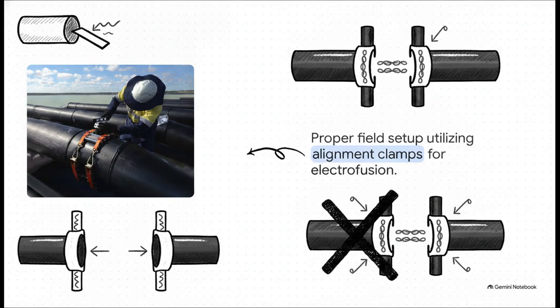But there's a catch. Relying on that internal expansion means your field setup has to be completely flawless. Meticulous preparation utilizing robust alignment clamps is mandatory here. And before we even reach that stage, scraping the oxidized layer off the pipe surface is an absolute requirement. Any ovality in the pipe or any slight misalignment creates excessive gaps. If there's a gap, the expanding melt simply flows into that void rather than building up the high internal pressure required to fuse those molecular chains. And no pressure means a failed weld, period.